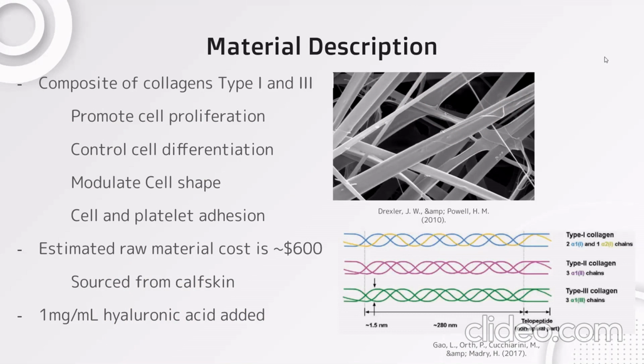So for our implant scaffold, we decided to use the composite collagens type 1 and 3 as our material. Type 1 collagen is found in skin, so is more readily available and is also cheaper than type 3 collagen. It also has higher tensile strength than the type 3 collagen. However, type 3 collagen we use in addition to type 1 because it has glycoprotein receptors on it that bind platelets to it, increasing the wound healing response basically around the implant site.